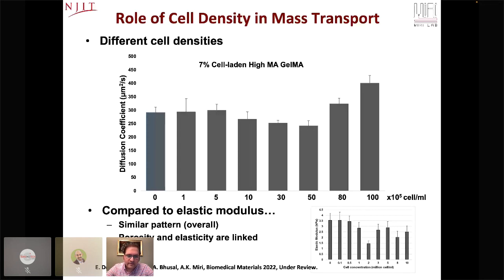And compared to elastic modulus, it gives you some idea that the porosity and elasticity are kind of interrelated. At some point, maybe the existence of the cells reduces the diffusion coefficient because they are filling the pores, but after a certain density, the presence of the cells maybe reduces the photo-cross-linking between the material bonding sites. So that might be a justification for why we have that sharp increase.